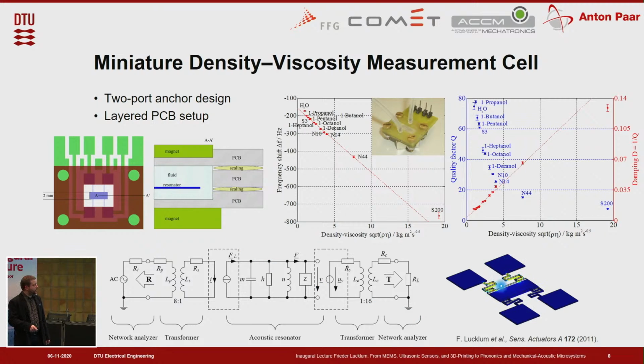So we have an in-plane motion again of this suspended plate, and therefore it's very sensitive to the density and viscosity of the liquid. And you can see the result in those graphs where we have a linear relationship between the frequency and the damping for different kinds of liquids over a wide range of densities and viscosities. And the whole setup is very inexpensive. It's just a couple of layers of printed circuit boards, 2 permanent magnets, and this structured metal resonator. So there's no expensive electronics or moving parts other than the vibrating element involved.